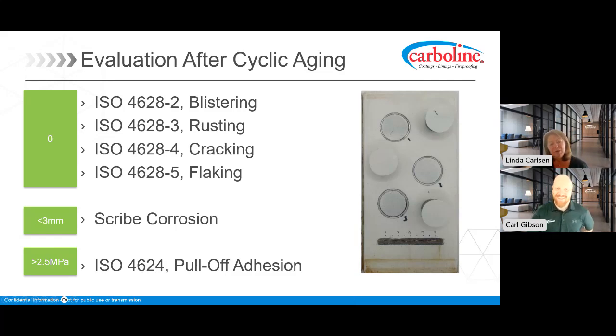Yeah, no, I've seen it. Many years ago, some engineer said that with zinc silicate systems you can get below 1 millimeter. That was the old cycle. Then you add a new cycle with the freezing cycle, and suddenly all the systems that tested below 1 millimeter were close to 3. So it is difficult. And you can imagine when you're sitting in these standardization committees, there will be a lot of discussions. Everyone has an opinion, and to agree on everything, it's a long way. It takes time. Yes. Yeah, definitely.